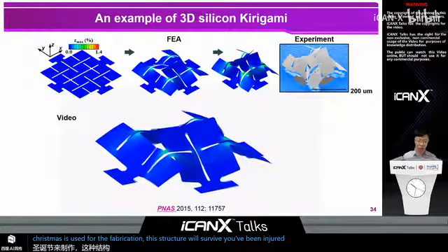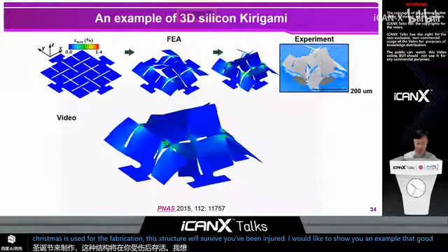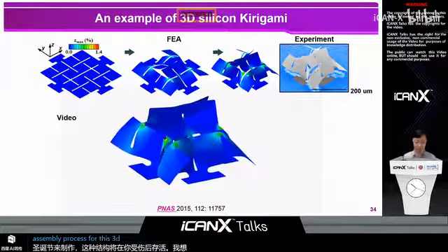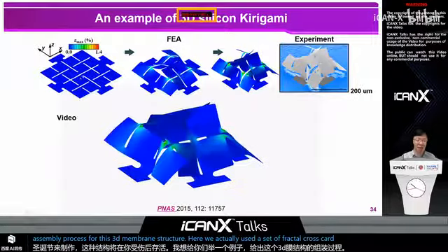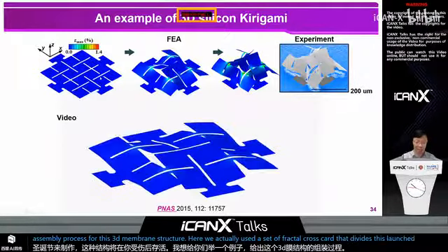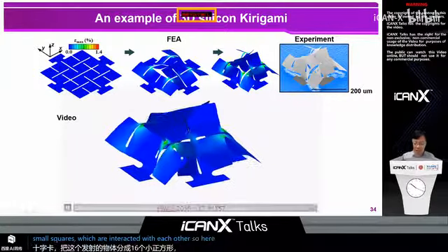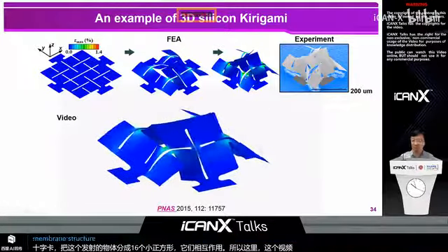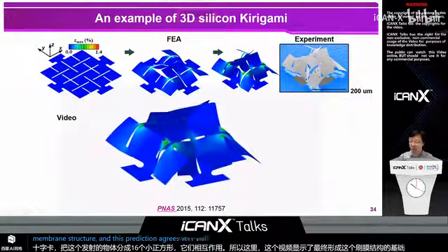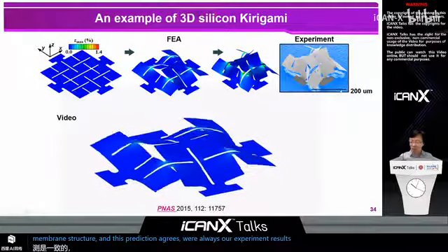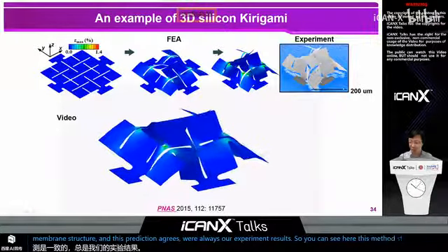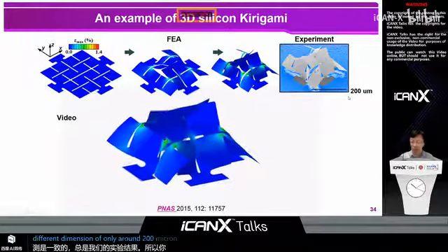Then I would like to show you an example that illustrates the assembly process for this 3D membrane structure. Here we actually use a set of fractal crosscuts that divide this large square into 16 small squares, which are interconnected with each other. So here, this video shows the deformation process to result in this final 3D membrane structure. And this prediction agrees very well with our experimental results. So you can see here, this mesostructure has a lateral dimension of only around 200 microns, and the thickness of the silicon is only around 300 nanometers.